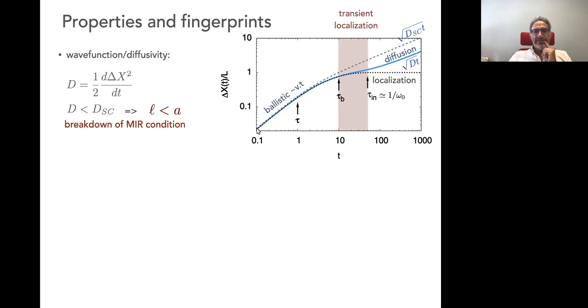It's shown here at short times. And by short, I mean shorter than the typical time scale of molecular vibrations. The carriers don't know that the disorder is moving because these motions haven't been activated yet. So the carriers will follow the localization curve. But then as soon as they realize that the disorder potential is shaking, they will start diffusing. Now, the consequence is that the diffusion constant and hence the mobility will be lower than the semi-classical one typically because of this time lag before it can start diffusing. And this is what allows the breakdown of this Mott-Ioffe-Regel condition, or having apparent mean free paths, just apparent mean free paths that are shorter than the lattice spacing.